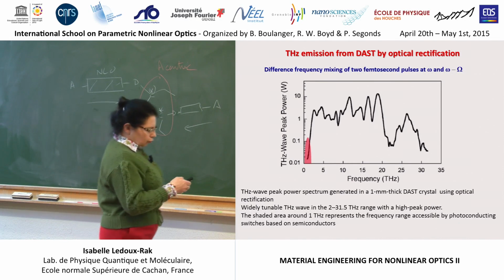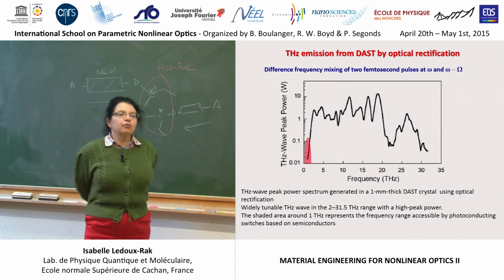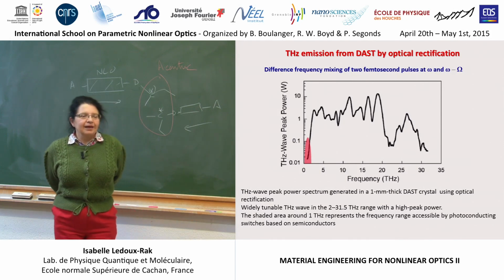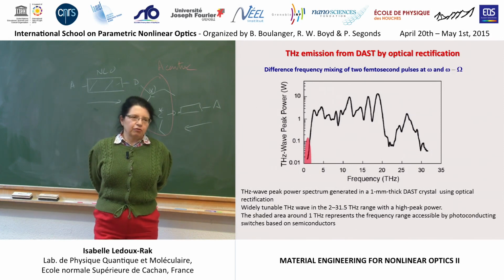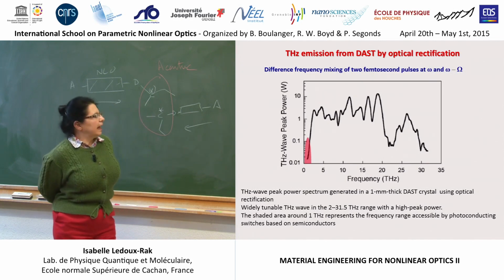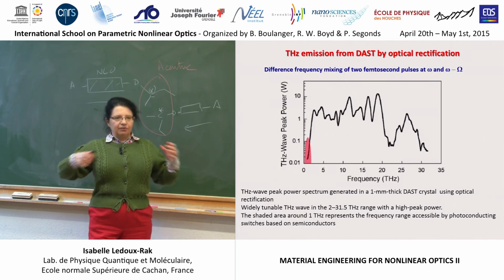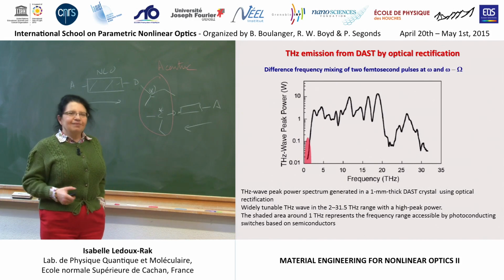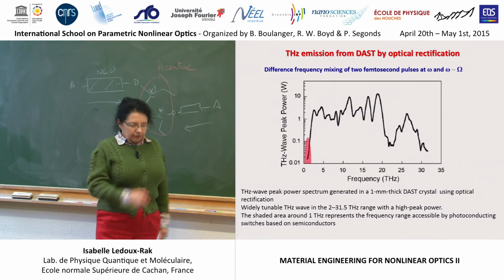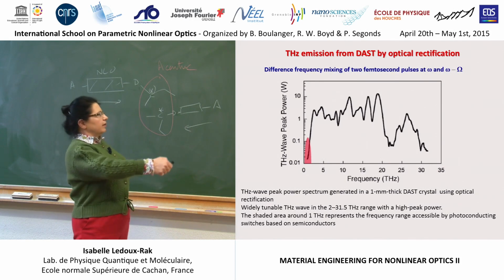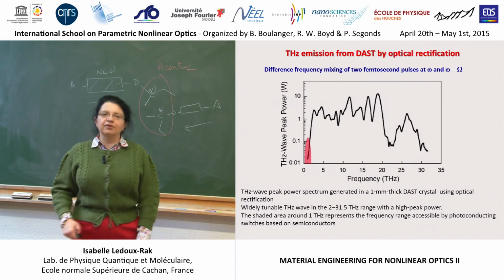emission range. The problem you will find with DAST as compared to polymers is that it is still a crystal, and it is very good, but it is difficult to make a waveguide structure. It has been made, but it is not trivial, and it is difficult to integrate with other circuits or devices because crystals cannot grow on any kind of substrate in a controlled manner. This is why DAST is mainly limited to the domain of terahertz emission, which is already quite a good achievement.